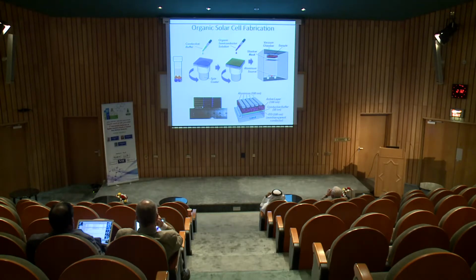And how do we actually make an organic solar cell? In the lab, we do not make large-area solar cells. We make a prototype which is quite small. As you can see here, we start with the donor and acceptor powder. We dissolve them in organic solvent, and then we deposit a few drops onto the ITO-coated glass substrate. When you spin, the solution spreads out to form a thin film, and the solvent evaporates and yields the thin film. The thickness of the film can be determined by the solution concentration and how fast you spin, and that can be used to control the film thickness.